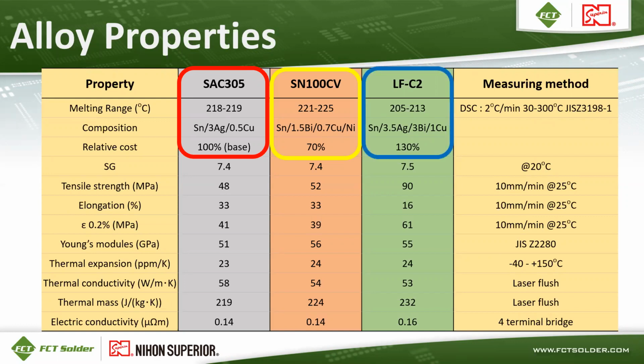And then LFC2 has a lower melting range, 205 to 213. So it can actually reflow in a profile with roughly 5 to 10 degree lower peak temperature. That is advantageous for anyone who wants to run a lower peak temperature or has sensitive components that maybe can't handle a SAC 305 profile. LFC2 does contain silver, bismuth, and copper, and therefore the cost of that alloy is about 30% higher than that of SAC 305.